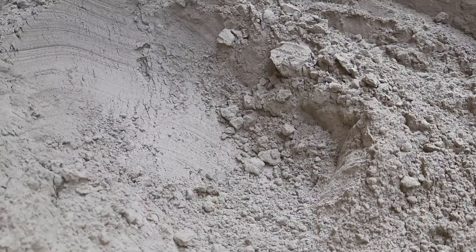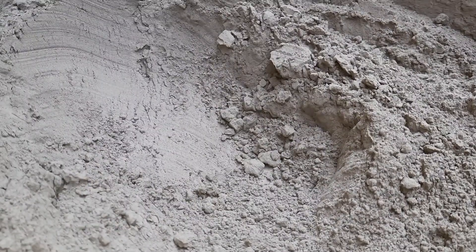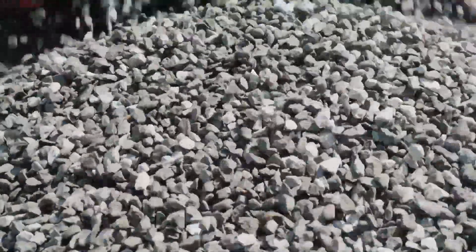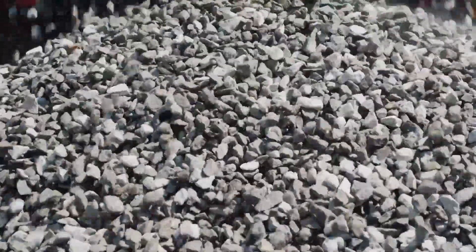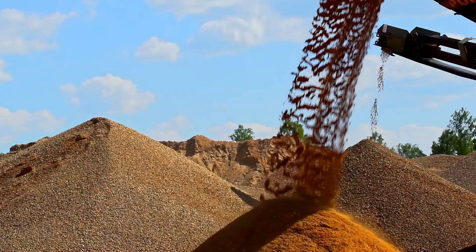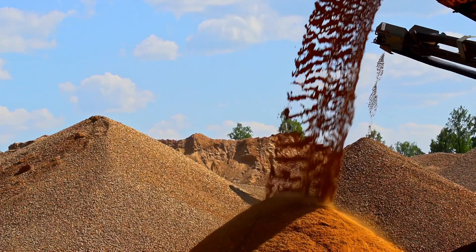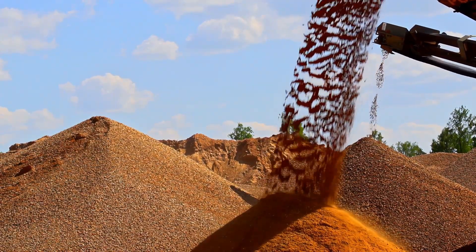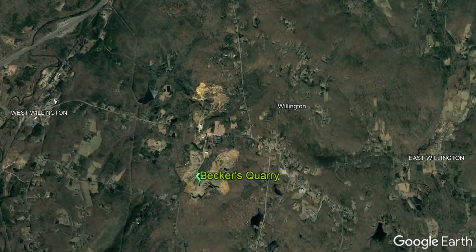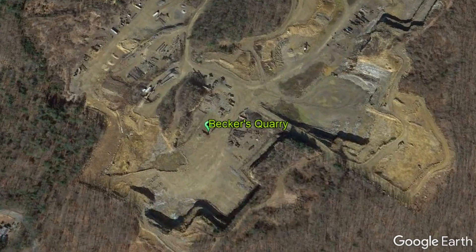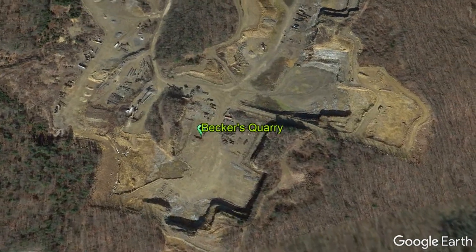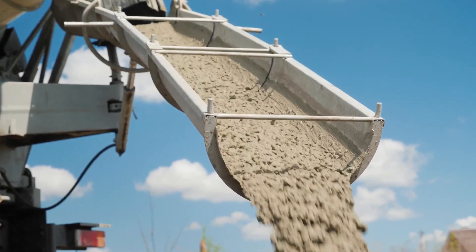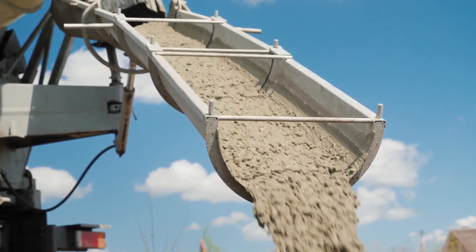Specifically, if pyrite-rich sedimentary rock or black smoker vents are buried underneath a substantial amount of rock, the heat and pressure will become sufficient enough to convert the host rock into metamorphic rock. This process also changes the pyrite into pyrrhotite. Concrete as a whole is composed of Portland cement, water, and about 70% rock aggregates, which are essentially gravel-sized rock particles. The pyrrhotite can thus get into the concrete if it occurs as a trace concentration within the rock aggregate. This is exactly what occurred when the aggregate was mined at Becker's Quarry in Willington, Connecticut, and used in concrete for some homes built between 1983 and 2015.